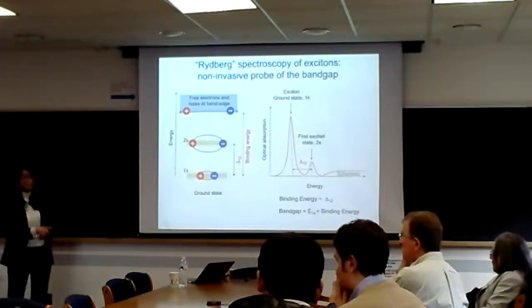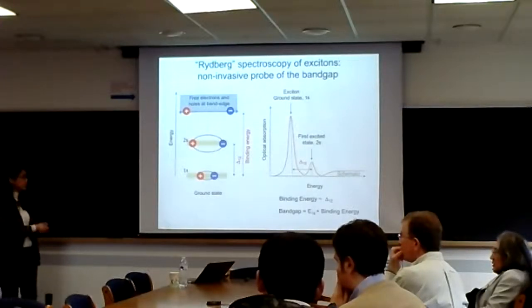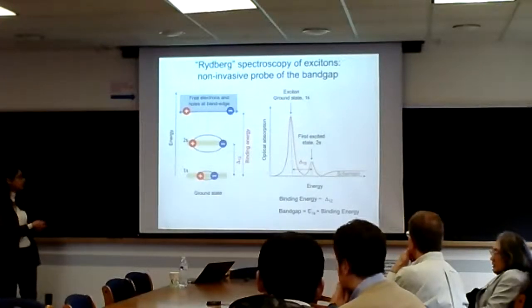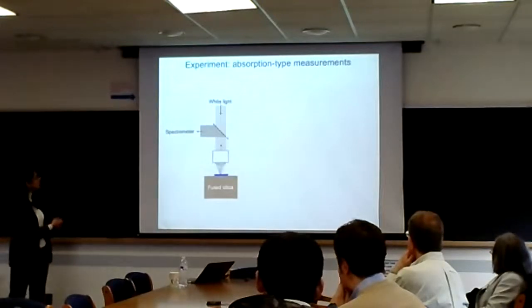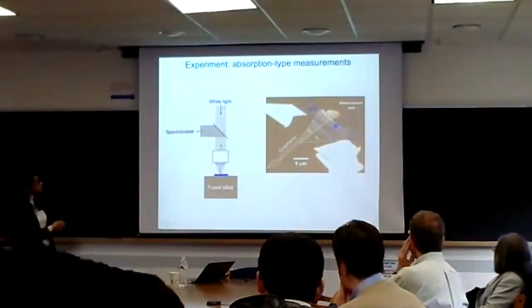So this way we can extract the quasi-particle gap only through optics. The experiment is fairly straightforward here. You use white light and you measure the reflectance contrast spectrum of this. So it's like measuring an absorption spectrum in this case. And you have a sample, something like this.